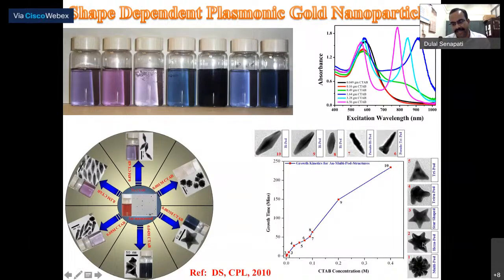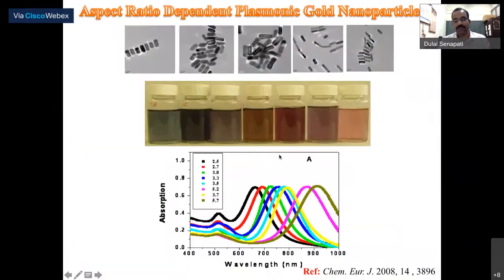And as the concentration increases, they are becoming more and more directed nanoparticles. And finally, at the highest concentration of the surfactant, here it is cetyl trimethyl ammonium bromide, we can make the gold nanoparticle as a bipyramid, which is very close to the rod.